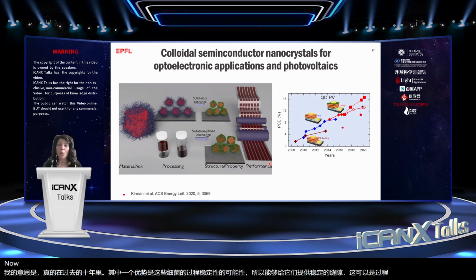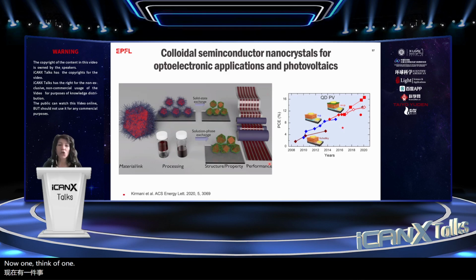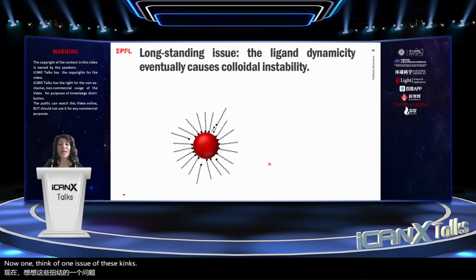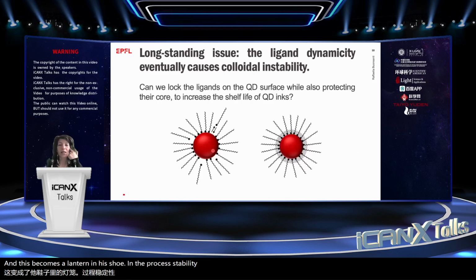Now, one issue of these inks is that the ligands that I mentioned at the beginning are in a dynamic equilibrium between the surface of the nanocrystals and the solution. And this dynamic equilibrium eventually causes colloidal instability, both long-term, but also if the solutions are too diluted or too concentrated. And this becomes eventually an issue in the processability of this material.